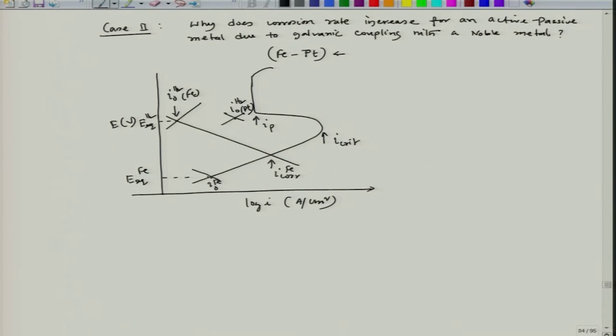The same is true here. If these two particular points are lying wide apart, then even if we add these two current densities, the mixed potential theory says the total rate of cathodic reaction should equal the total rate of anodic reaction at a mixed potential. But since these two current densities are wide apart on a log scale, that addition would be very negligibly felt.